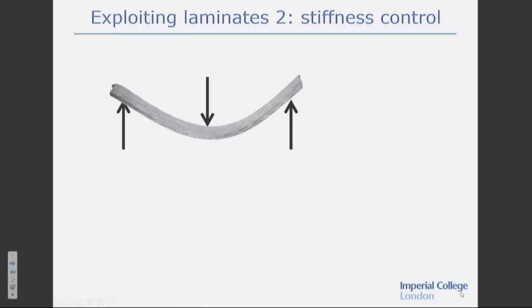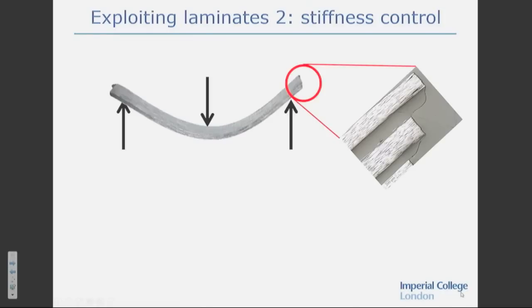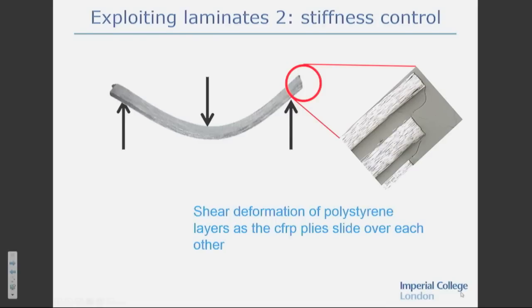And now I'm going to tell you that we did the room temperature one first, then we did the elevated one and lost all the stiffness, and then we unloaded the specimen and did it at room temperature again, and that's there. We recover the stiffness totally. This is a view of the specimen in the large displacement state at the elevated temperature. And if we looked at the ends, we see that sliding behavior that we saw before in the test that Jing did for me. It's that shear deformation of the polystyrene that allows this to happen.